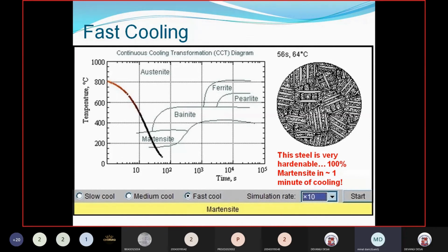Normally tempering is not done at as high a temperature as the austenizing temperature range. It is done around 150 up to 600 degrees Celsius. Then you hold the same way, 1 inch for 1 hour, and then do air cooling. Whatever stresses are generated in hardening, you have to relieve. So with tempering, hardness will decrease a little compared to your hardening treatment, but not by much. If you get 62 HRC in hardening, then you will get 58 to 60 HRC.